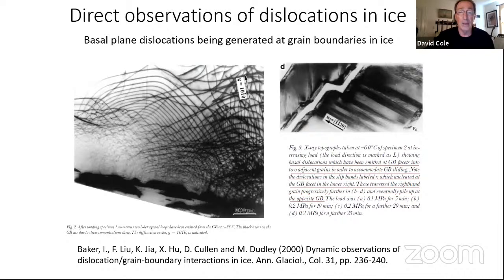If we look at freshwater ice, where things are a little more clear, a colleague down at Dartmouth, Ian Baker, has produced some just marvelous micrographs showing dislocations being produced along grain boundaries. So all these black lines are individual dislocation cores that we see emanating out from this darker area. Here is a grain boundary where the stress concentrations are high enough to actually generate the dislocations.